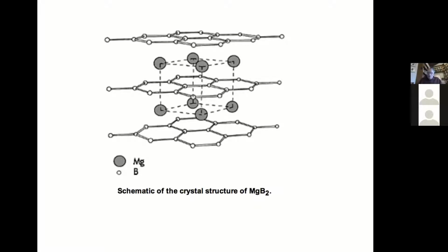I'd like to make a few comments about magnesium diboride, this roughly 40 Kelvin surprise superconductor that Akimitsu discovered, and this is again thinking about what I would call intermetallic materials that satisfy approximately a kind of valence rule. And within the Zintl way of thinking about materials, you look at this diboride structure. It's called the aluminum diboride structure. In magnesium diboride, you have divalent magnesium, and you have these boron sheets that are essentially graphitic-like.